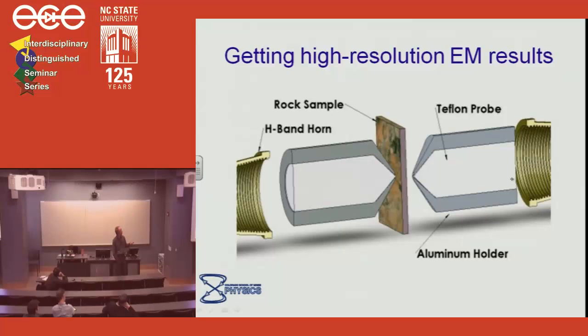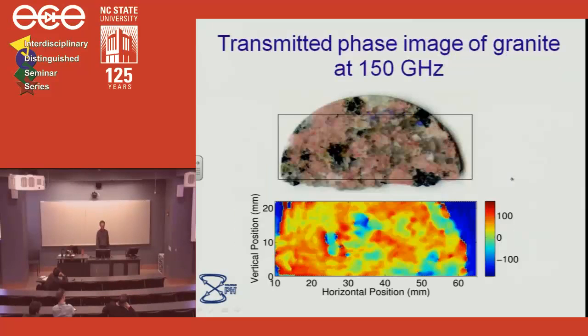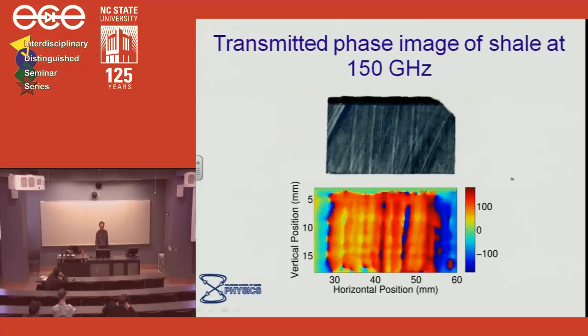But basically, we bring the source field close, and we bring the receiver close, and then we just scan the sample through the beam. And you get all kinds of interesting stuff. So this is what I showed you before, and you can directly correlate the phase changes. These phase changes correspond to changes in index of refraction, which we've checked with the actual values of the index for the materials in this heterogeneous rock. So we started at 150 gigahertz, and we've moved up to higher frequency.